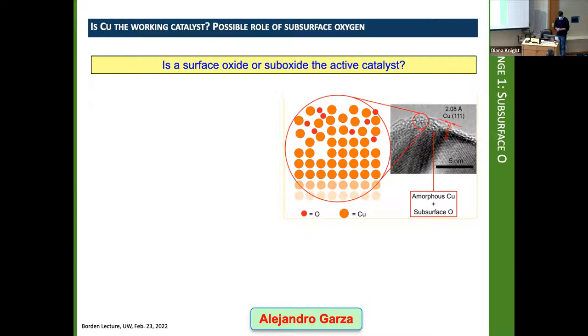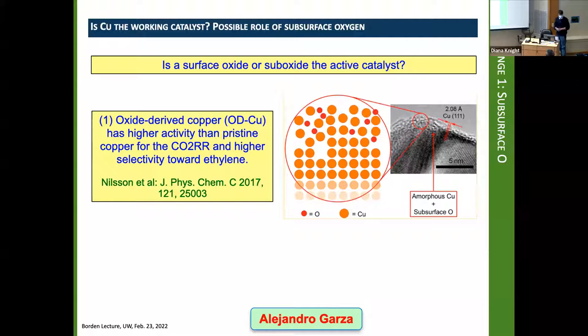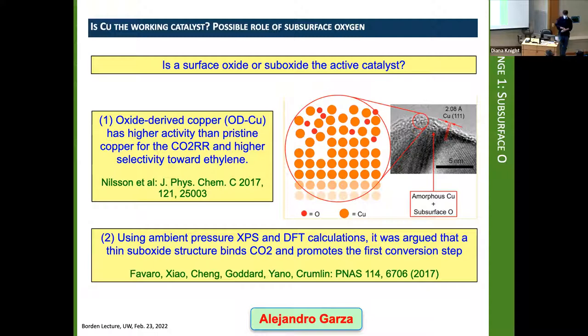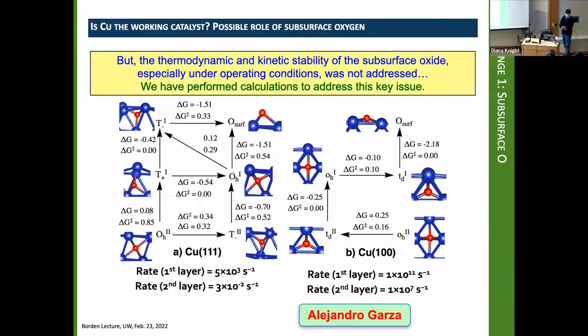And there is some experimental information that suggests that oxide-derived copper has a higher activity than pristine copper. So in other words, take copper oxide and reduce it. And using ambient pressure XPS and density functional calculations, it was argued that a thin suboxide structure binds CO2 and promotes the first conversion step. And so those are things that suggest maybe the assumption of copper is not ideal. But the thermodynamic and kinetic stability of the surface of the suboxide, subsurface oxide has to be considered, and it has to be considered under operating conditions.